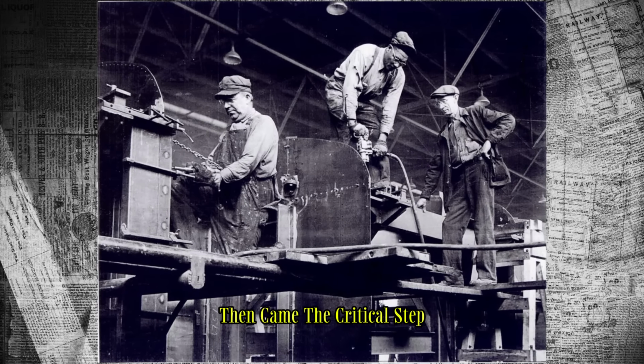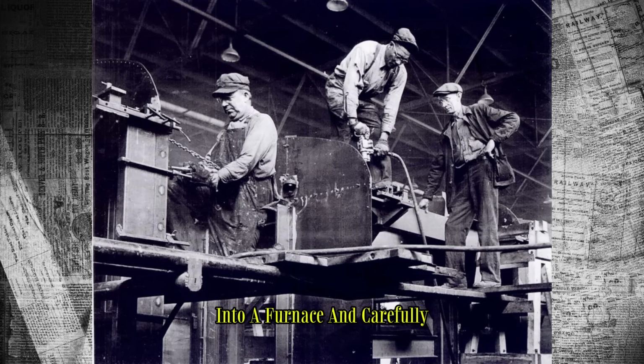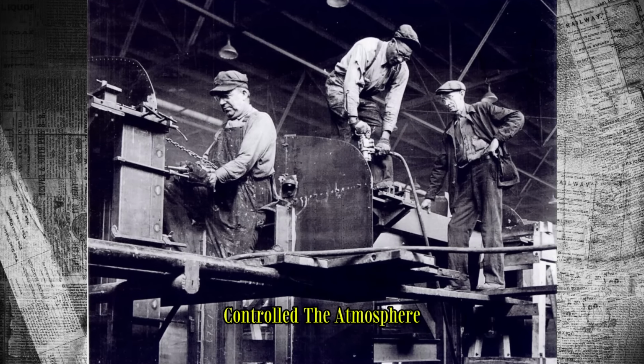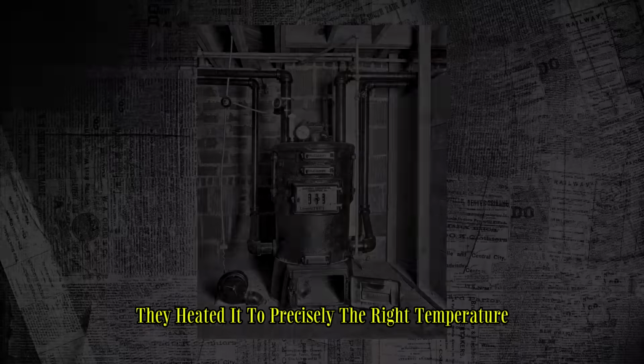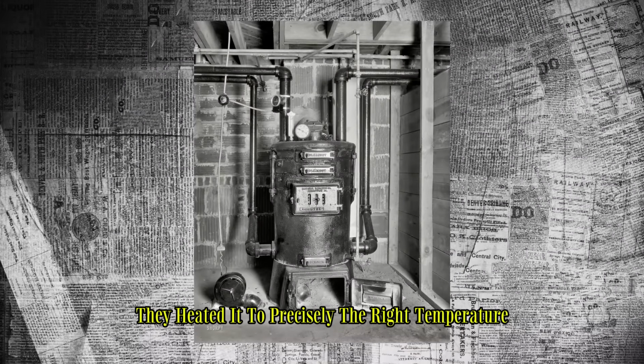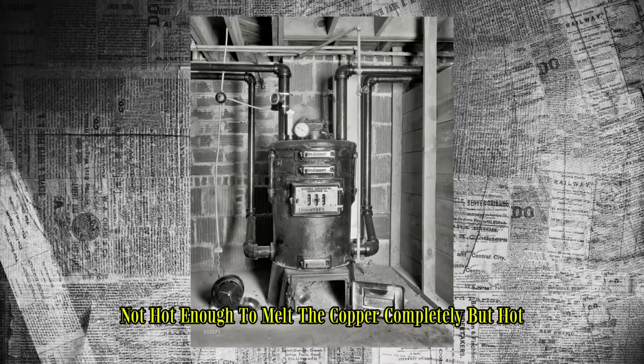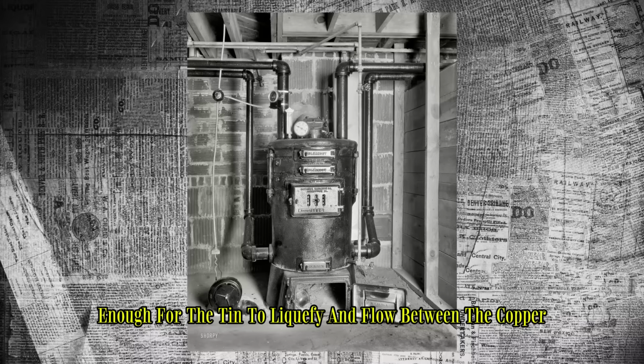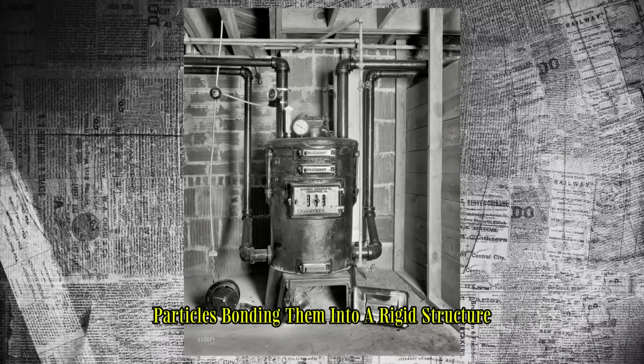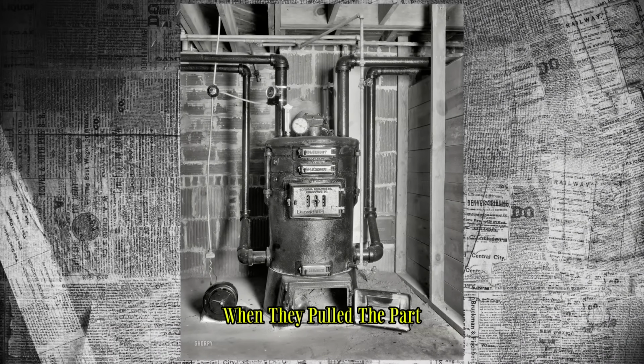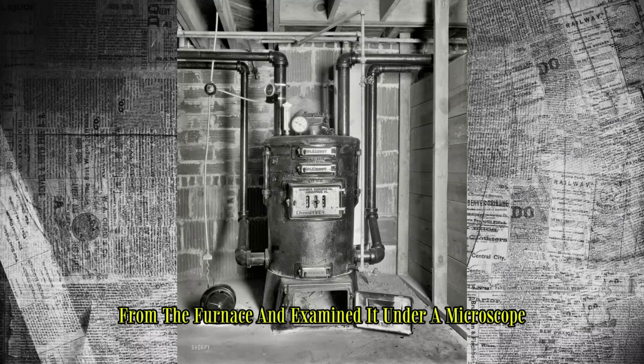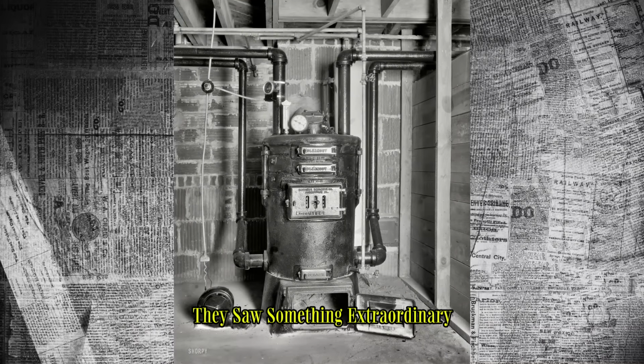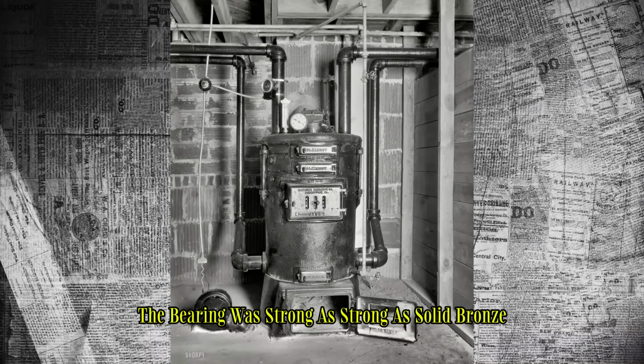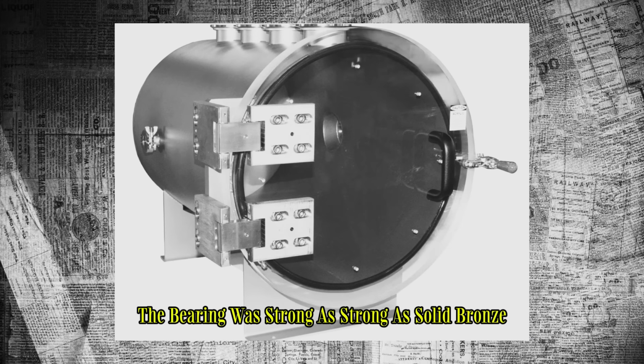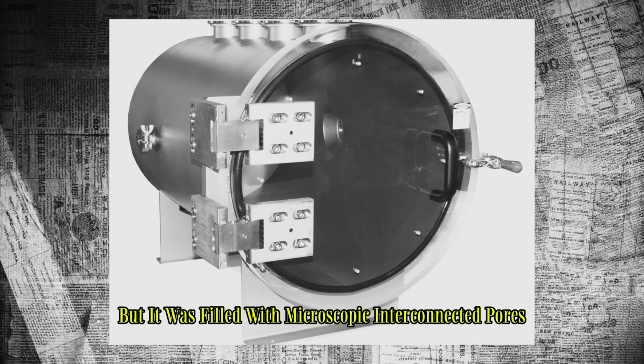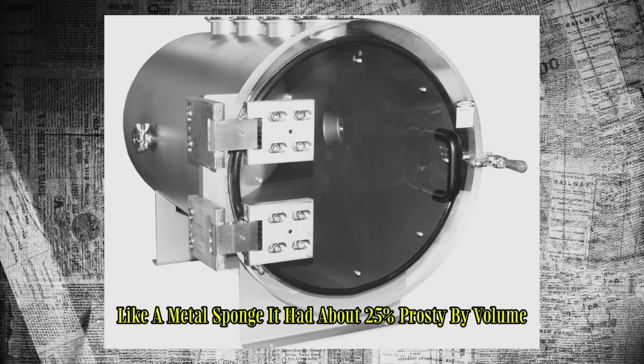Then came the critical step. They loaded the compacted part into a furnace and carefully controlled the atmosphere, removing nearly all oxygen. They heated it to precisely the right temperature. Not hot enough to melt the copper completely, but hot enough for the tin to liquefy and flow between the copper particles, bonding them into a rigid structure. When they pulled the part from the furnace and examined it under a microscope, they saw something extraordinary. The bearing was strong as solid bronze, but it was filled with microscopic interconnected pores, like a metal sponge.